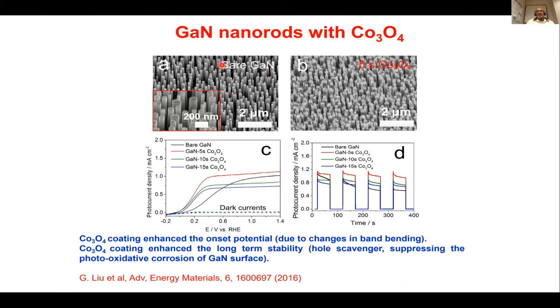We made bare gallium nitride nanowires, my student made them by using plasma etching from the top down, and then tried to look at the photocurrent density as a function of the overpotential. He is able to show that by coating the gallium nitride with cobalt oxide, we're able to get a very stable performance. But still gallium nitride, as I mentioned, is not the best material. And we're exploring materials like indium phosphide and other semiconductors as well.